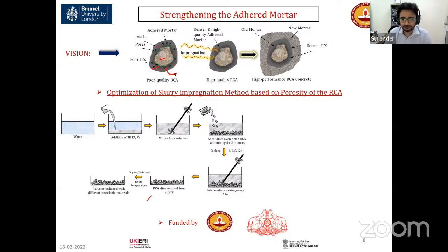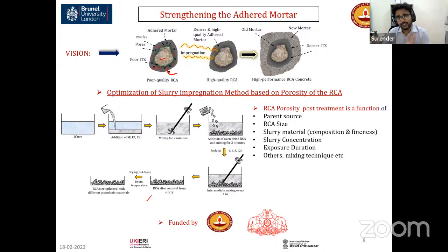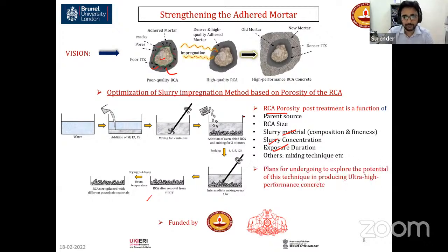of this adhered mortar is a function of many things. First, from which source we are getting the aggregates. What is the size that we are considering? The porosity is also a function of the slurry material, because if you have microsilica and fly ash, both will have different fineness. And if I compare with GGBS, they will all have different compositions. And then similarly, how much slurry concentration should there be? For how long should we keep the aggregates in the concentrated solution? And also whether you are able to mix the slurry effectively or not. So all these things will be affecting the porosity of the recycled concrete aggregate and thus the quality of the aggregate. So currently we are working on it.